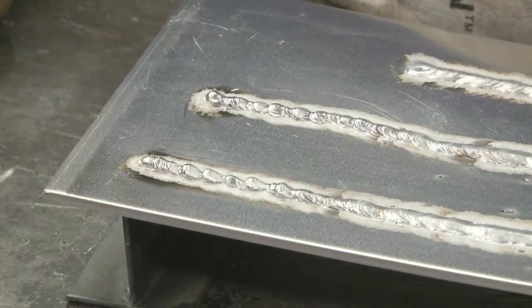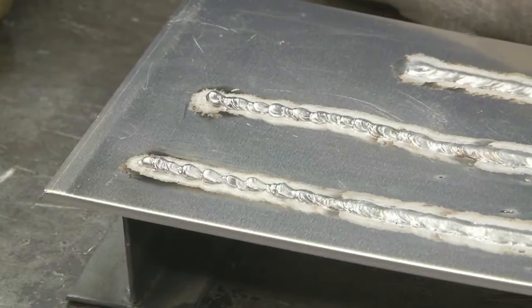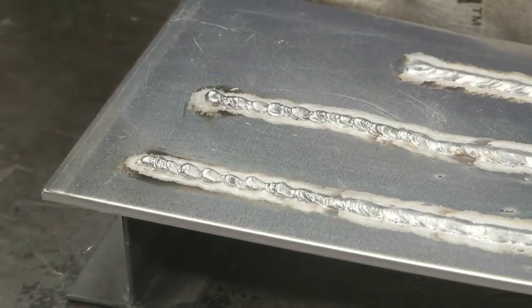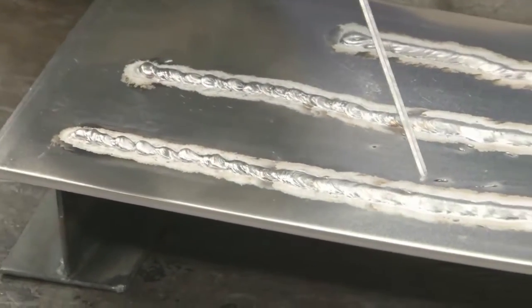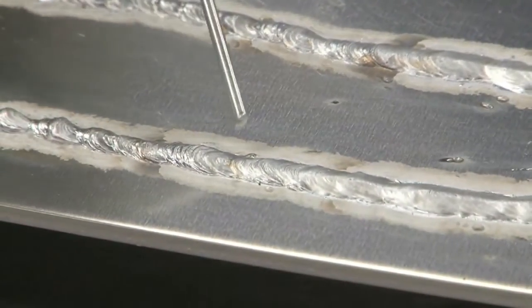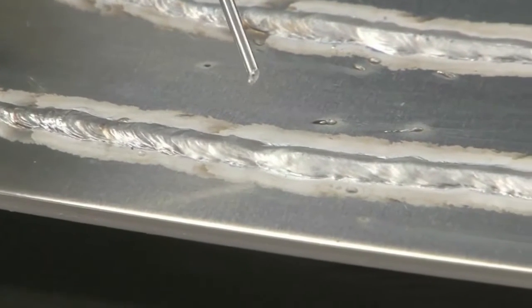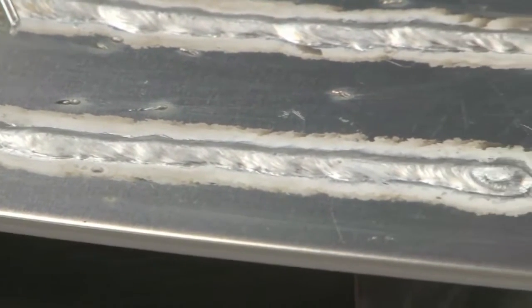One of the advantages to gas metal arc welding aluminum is we're using direct current electrode positive, or reverse polarity, which gives us a cleaning action on the aluminum. And as you can see here, next to the weld bead, we see that cleaning action busting up the oxide layer on the aluminum itself, allowing us to make the weld.